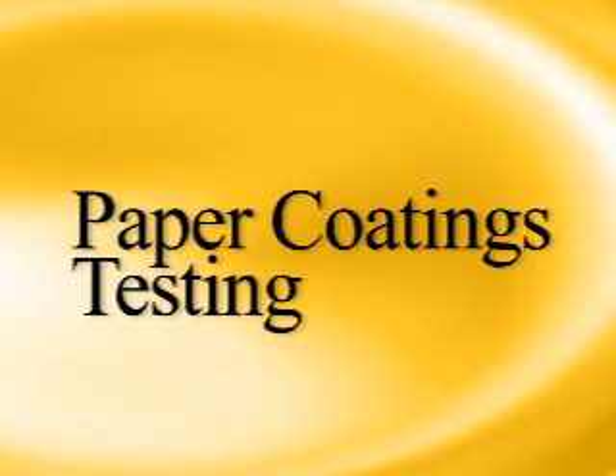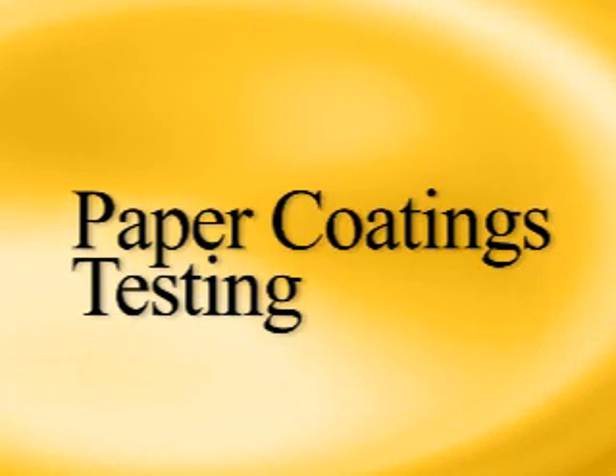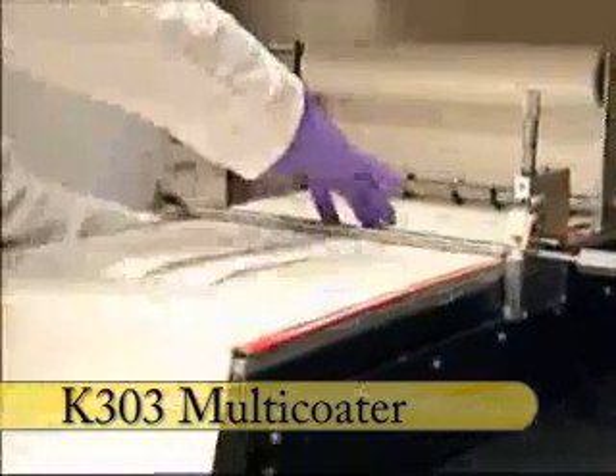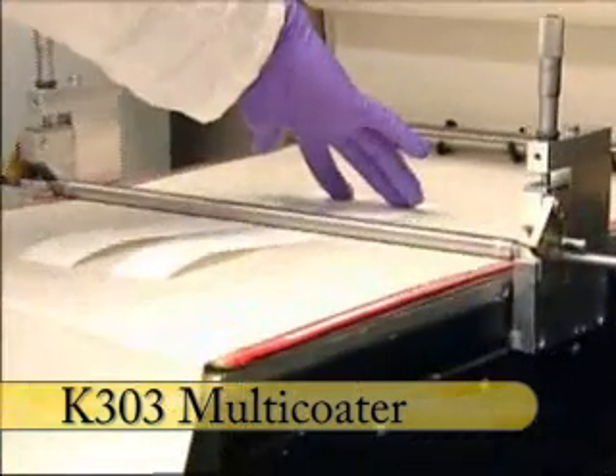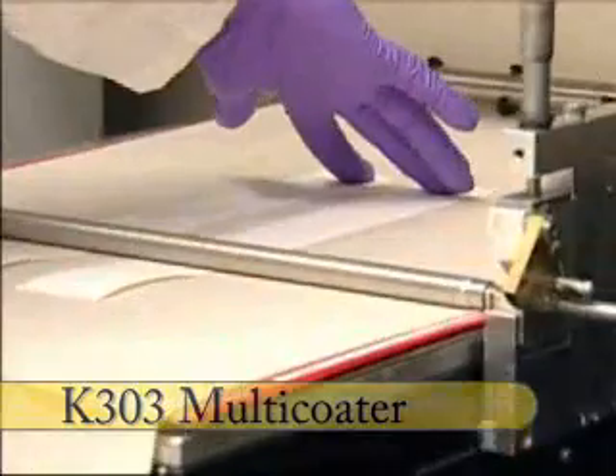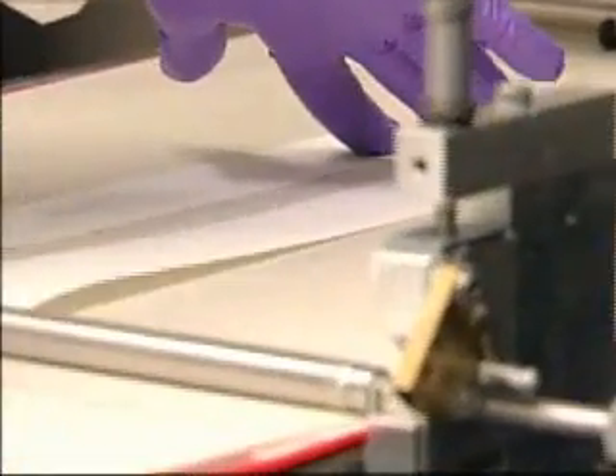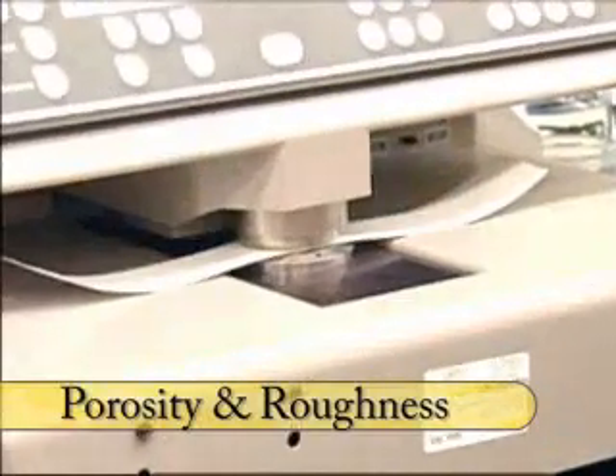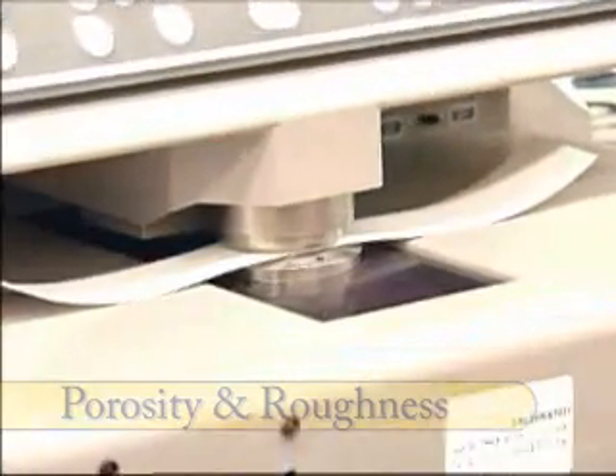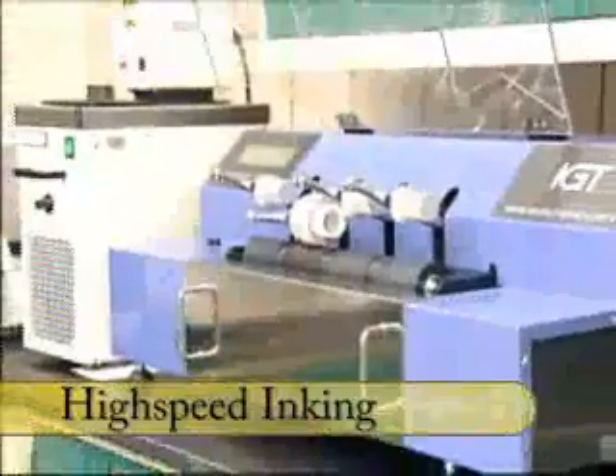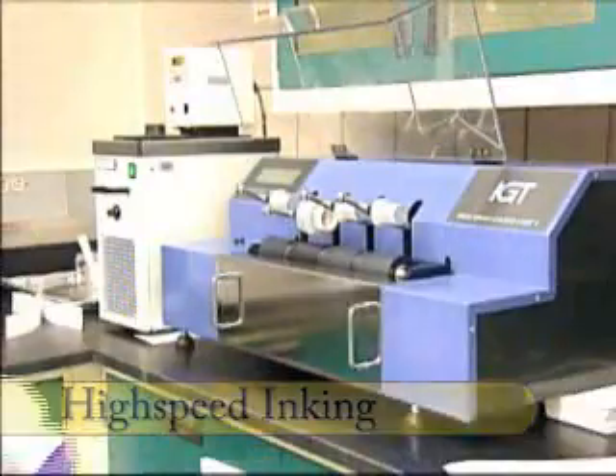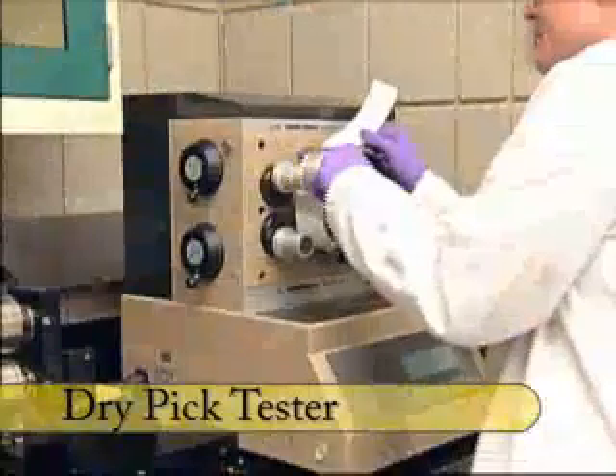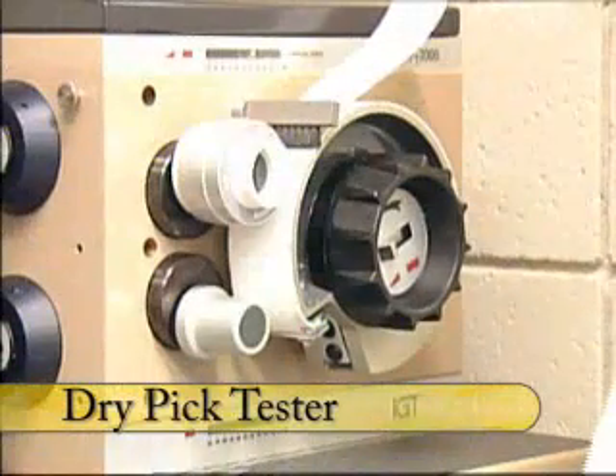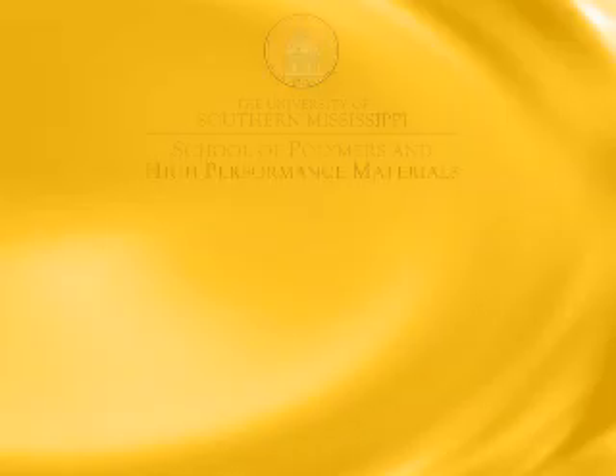VOMM-based latexes have been formulated into paper coatings following a process similar to producing architectural coatings. The paper coating is applied to the test strips using a wire-wound rod and cured at 105 degrees Celsius for 1 minute. The coated paper is tested for porosity and roughness using a Parker Print-Surf, and for dry pick strength following a TAPPI test method using an IGT inking machine.